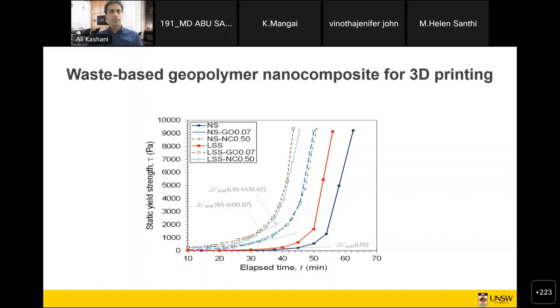So as you can see, adding lead smelter slag helps with that early strength development, and adding those graphene oxide and nanoclay also helps. And graphene oxide, as you can see, is pretty good in terms of that. If you increase the percentage, you can even get better, up to some limit, obviously. Otherwise, the material is not going to be workable or extrudable.